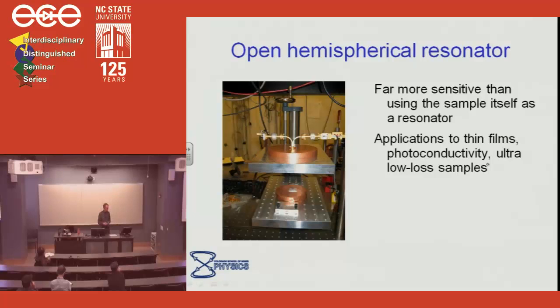For example, if we put a substrate with a thin film in there, with a film on top, and then turn it over, we see a big difference. So that perturbation allows us to actually back out the dielectric properties of the thin film, even though that film is probably 1/5000th of a wavelength. So that's the latest thing.